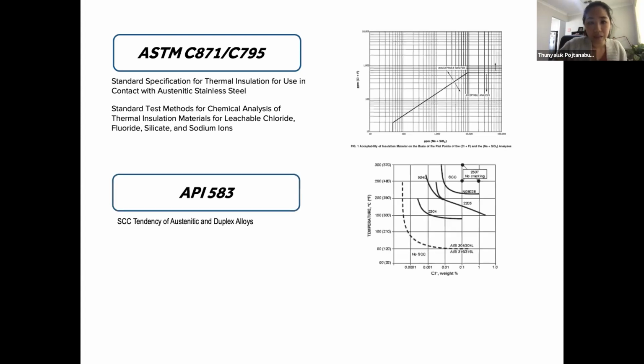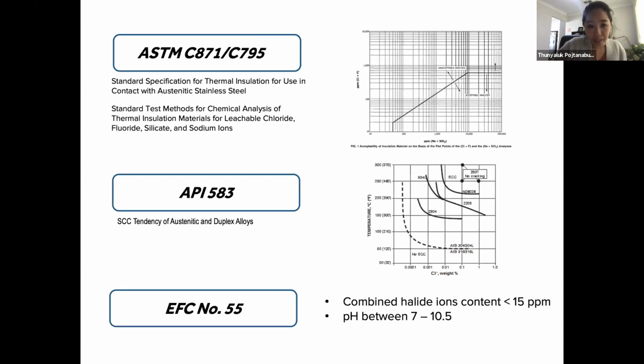Another guideline that has been used is the API 583. There's a figure in that standard that shows the diagram of the chloride content with the operating temperature and the compatibility with different materials with respect to the risk of stress corrosion cracking. The EFC guidelines number 55 also suggested that the acceptable insulation material should have a halide ion content, in this case both chloride and fluoride, less than 15 ppm, or a pH between 7 to 10.5. So these are the existing industry guidelines for asset owners or for the end user to rely on when it comes to the selection of the insulation material for different applications. So we can see that it focuses on the chloride and the pH.